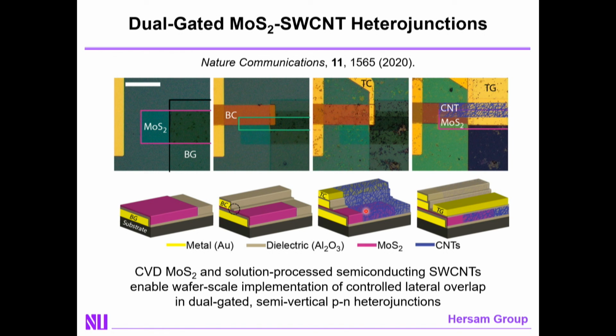As a result, they are easily gated due to weak dielectric screening. Moreover, because it's a mixed dimensional heterojunction, the screening is weaker on the 1D side than the 2D side, giving you an asymmetry in the gating in a dual gated geometry.